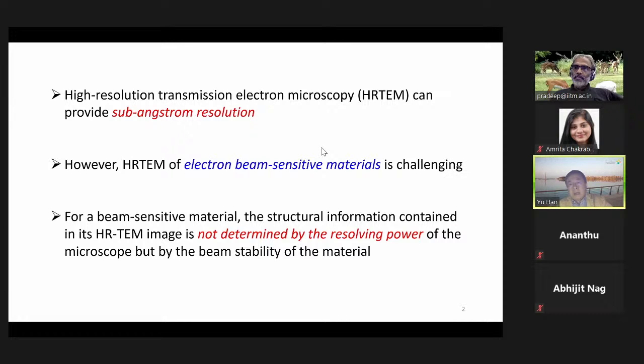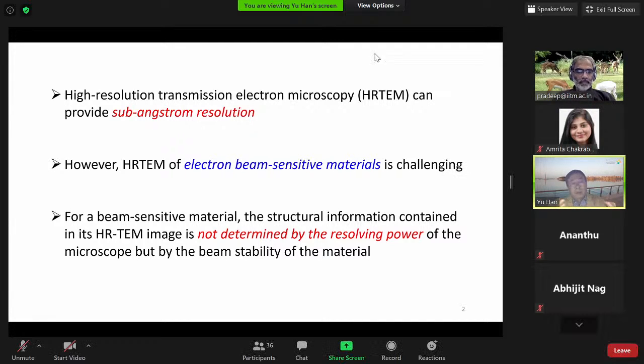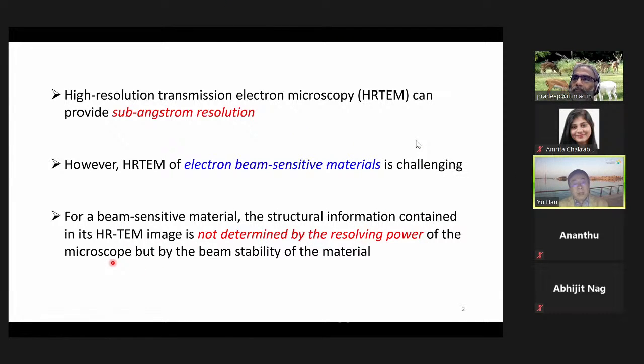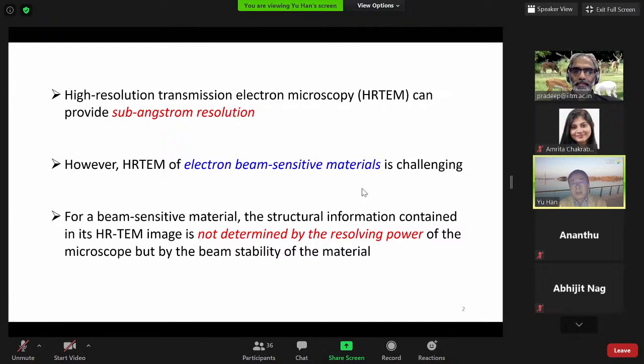Actually, many materials have this problem. For example, porous materials like zeolites, MOFs, COFs, organic crystals, polymers, proteins, supramolecular structures, and hybrid materials. We call this kind of material electron beam sensitive materials, or simply beam sensitive materials. For a beam sensitive material, the structure information contained in the HRTEM image is not determined by the resolving power of the microscope, but by the beam stability of the material. That is, how much structure integrity can be preserved under the imaging conditions. The more severe the structure damage, the less structure information we can see, right? Makes sense.